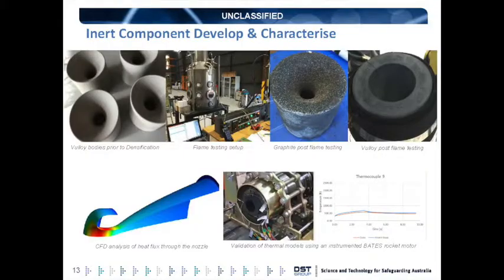It's a similar process with nozzle development. So nozzles in rocket motors are typically made of graphite materials because it's cheap. However, over the course of the operation of the motor, you'll start with a fairly narrow throat, which due to the erosion rate will start to actually change in size, opening up, which drops the pressure inside the case. So there's a bit of a trade-off there. Typically, they also contain quite a bit of the overall mass of the system as well.